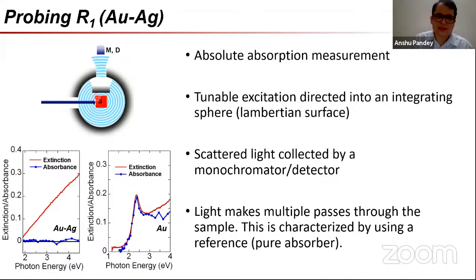What is odd about this resonance is if we try to look at it by, say, probing how it interacts with light, we find that there are a few unusual things. Firstly, we have taken a tunable excitation, which is directed into an integrating sphere over here. So this provides a Lambertian surface. The sample is stored inside a cuvette, so it scatters light, and that scattered light is collected. What we find with AuAg is that it has no tendency to absorb light. Its absolute absorbance, as far as we were able to measure, seems to be a total zero, even though it has a large extinction. In contrast, a normal metal particle is a very good absorber of light.